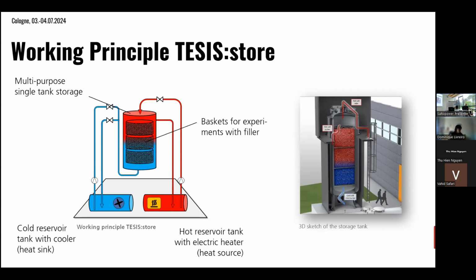And so we can pump hot salt here into the storage tank to charge it, and then the cold salt will be pushed out at the bottom and flow back to the cold tank. As we are testing a thermocline concept, which means we have a region with a temperature transition, this also means that at some point hotter salt will be coming into the cold tank. And the other way around, when we discharge, at some point the exit temperature will drop, and therefore we have an immersion heater in the hot tank to compensate for this temperature decline.